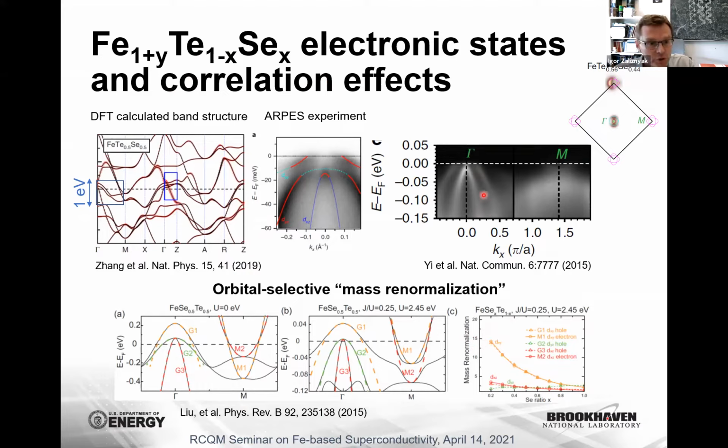And it was also shown directly by Mingyi that the coherence of the dxy band goes away upon warming, in qualitative agreement with the predictions of DMFT and with our observations of localization of one of the electrons. So the effects of strong correlations are extremely important and lead to decoherence of electronic band structure near the Fermi level in this material family.